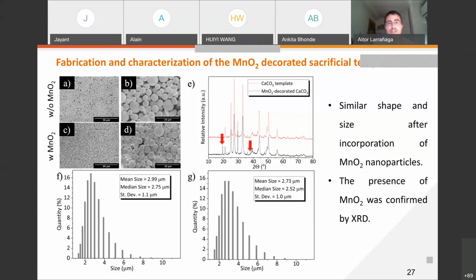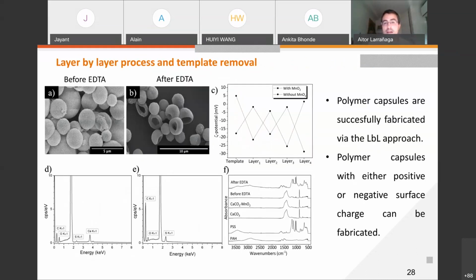So after the successful fabrication of the calcium carbonate template and the incorporation of manganese dioxide nanoparticles, we proceeded again with the layer-by-layer approach. And here again, we found this change in zeta potential of our particles as we were incubating the particles with positively and negatively charged polyelectrolytes. Again, as you can see in the scanning electron micrographs, we obtained the characteristic shape of the hollow polymer capsules. This shape is collapsed due to the high vacuum that is applied in the SEM observation. And again, to confirm the successful removal of the sacrificial template, we performed some EDX and FTIR spectra, where we confirmed that the calcium carbonate template was completely removed from our capsules.